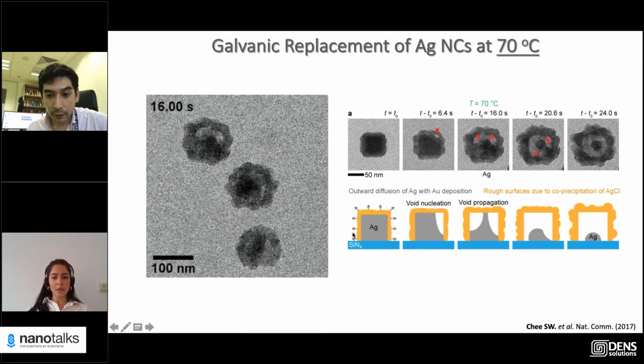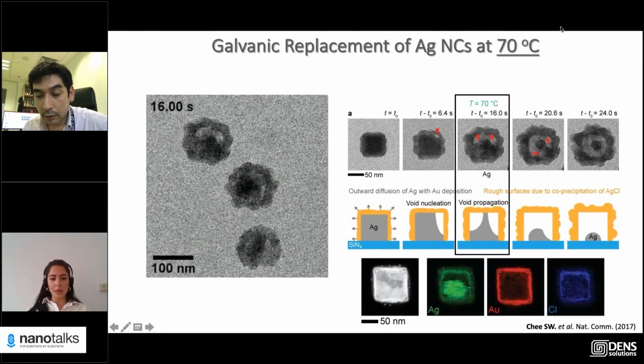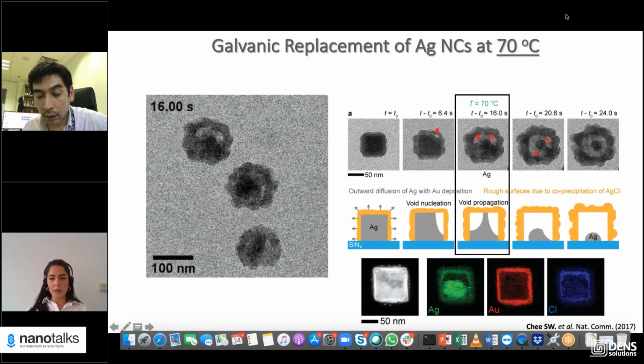Okay, but if you look at those elemental maps, it's a bit small. The red one is gold. The green one is silver. Because there it does seem as if the silver, at least the chloride, is on the inside of the gold. If you look at those elemental maps, the chloride square is much smaller than the gold square. So there would be silver chloride inside as well, which is logical, but you did not touch on it.